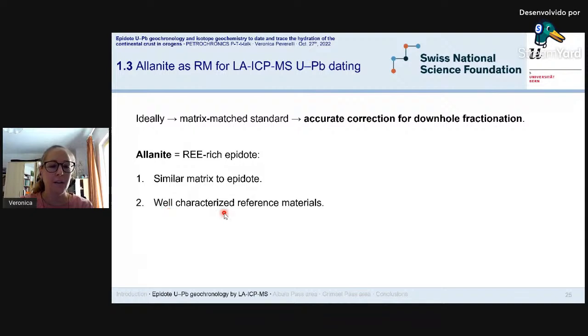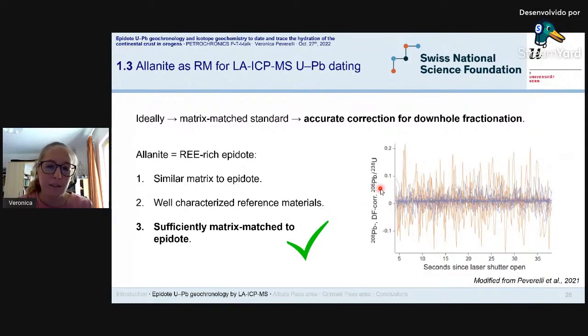And there exist well-characterized allanite reference materials. But we actually have to prove that epidote and allanite are sufficiently matrix matched. And we did so by plotting the lead-206 to uranium-238 ratios of single analyses. So each color is one analysis during ablation, which begins here and ends there, corrected for downhole fractionation using allanite as a reference material. So the concept is that if the patterns are flat and they overlap, then the correction for downhole fractionation is accurately carried out. And this is the case for epidote using allanite as a reference material.